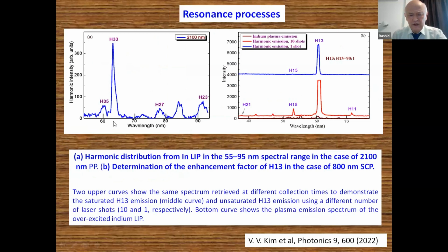Here I just show pictures of the strong resonance harmonic in the range of 62 nanometers in the case of indium plasma, when we use 2100 nanometer, and the same when we use 800 nanometer radiation. The overall ratio between this harmonic and the neighboring harmonic is in the range of 100, which is quite sufficient to consider this harmonic as a single coherent source of radiation.